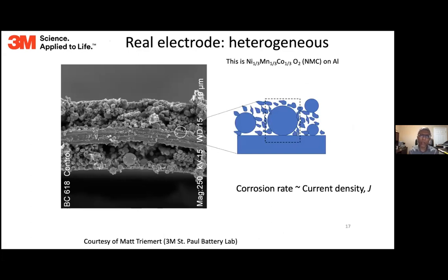But to understand what's going on with the system, let's look at the inside of the battery, any battery. Here is a picture of the cathode, an SEM picture. This solid piece is aluminum foil that's maybe about 15 microns thick. And you can see the active electrode material. In this case, it's known as NMC, nickel manganese cobalt mixed oxide, with a lot of carbon additives to make the electrode conductive. So it's a pretty complicated structure. If you simplify it graphically, this is what it looks like.